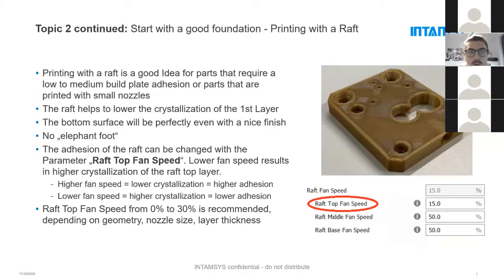To continue with topic number 2, we do recommend to print with a raft for any parts that require a low to medium adhesion or that are printed with small nozzles like 0.25 millimeter. To be honest, I'm not the biggest fan of printing with a raft, but on PEEK it definitely makes sense. Due to crystallization that you can have within PEEK, you can have a bad adhesion, which is good to print with a raft. Later on, I will speak a little bit about layer adhesion, crystallization, and so on, and then you may understand it a little bit easier.